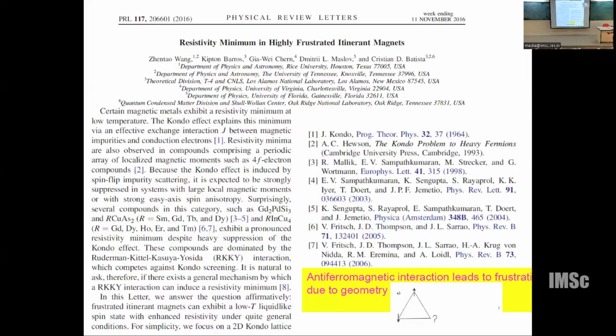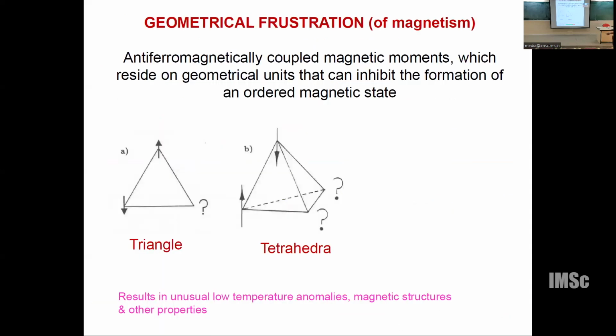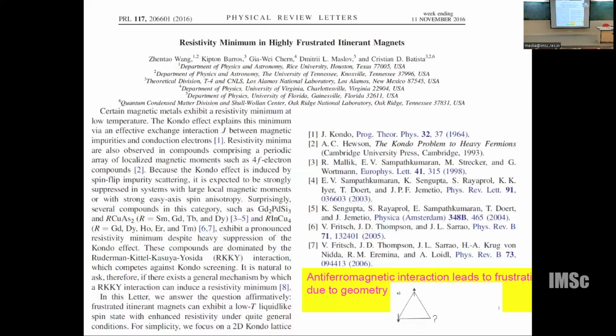So this was theoretically taken up after 20 years by a very well-known group, C.D. Batista. You must know C.D. Batista. He picked up our work and was motivated by it. He produced a theory for the event that there is geometrical frustration. By geometrical frustration, I mean that if you have a triangle and put magnetic ions here, if you ask them to order ferromagnetically, it's easy. But if you ask them to order antiferromagnetically, this fellow will not know what to do. This fellow will get frustrated. Same thing with the tetrahedra here. So it will be very, very problematic. So this leads to frustration. It's called geometrically induced frustration of magnetism. Let me leave it like that. He produced a theory of a combination of geometrical frustration and magnetic moment.